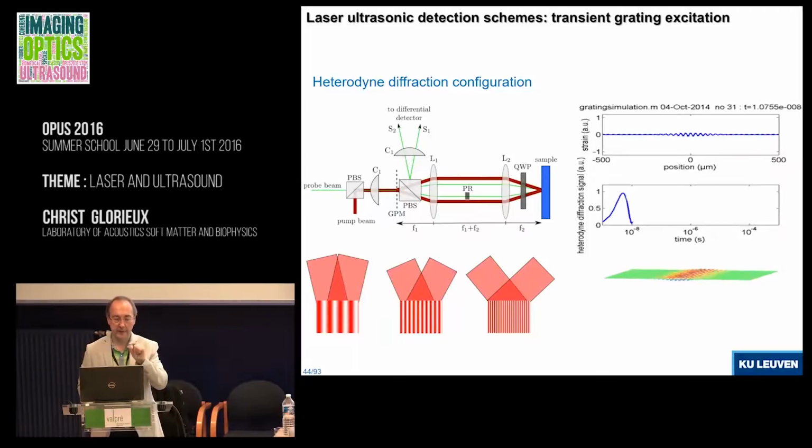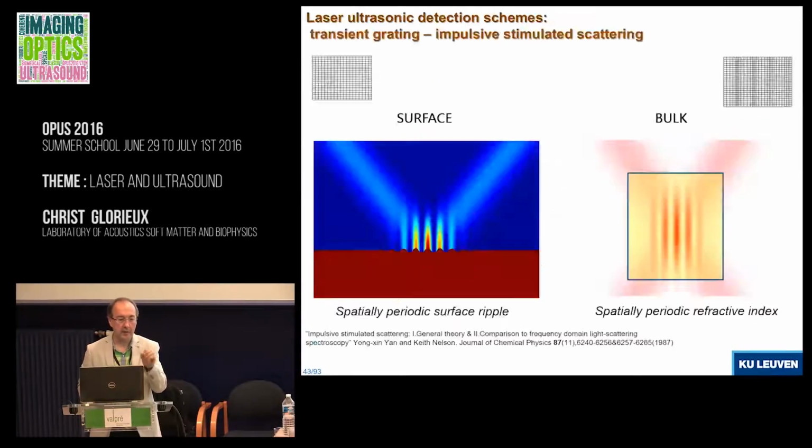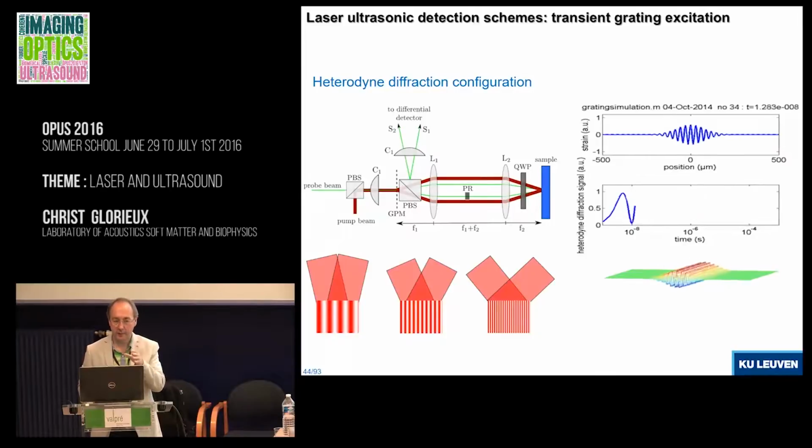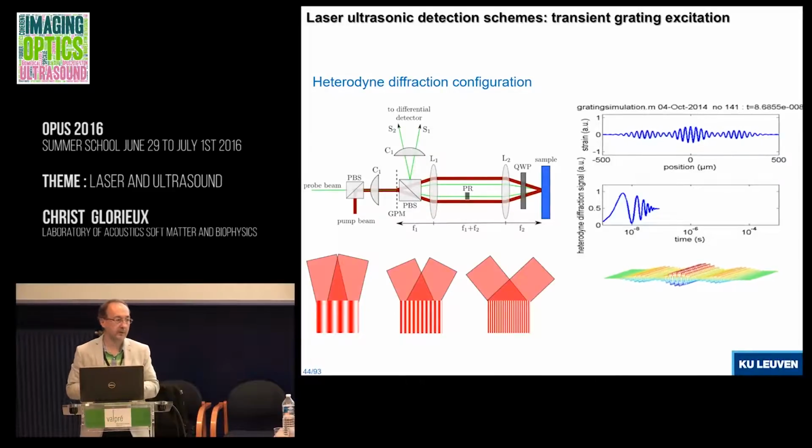So diffracted and reflected. Now you have interference between a strong reflected beam, because it's a strong probe beam, and of course a weak diffracted beam, because diffraction is very weak, and they give a beating. When you mix a weak beam and a strong beam, it's called heterodyning, and the changes of optical phase of the weak beam are amplified, and you get more sensitivity to displacement.